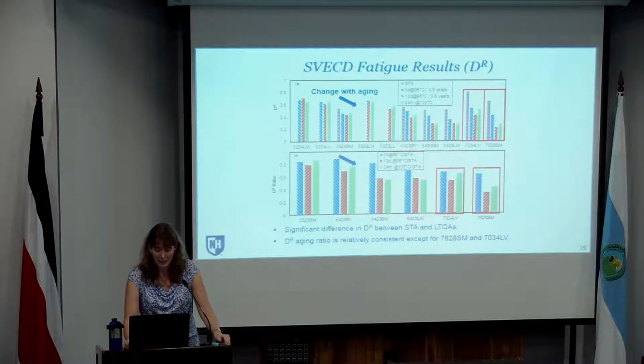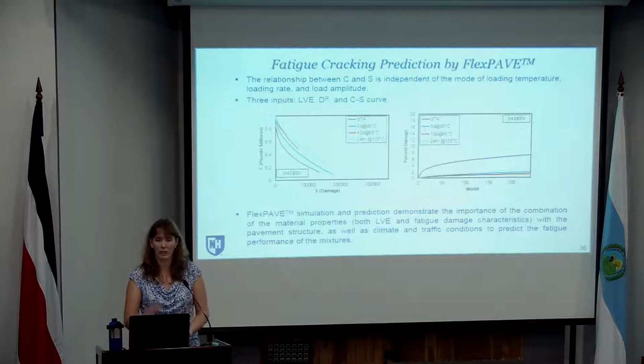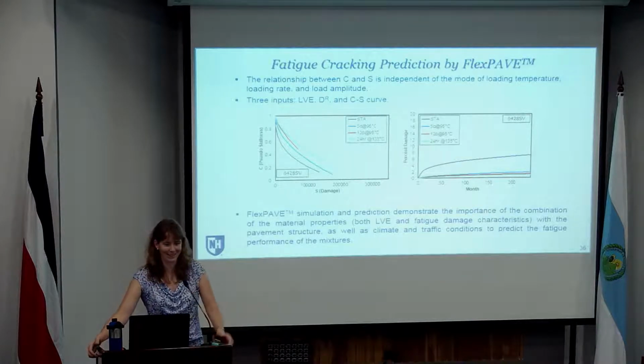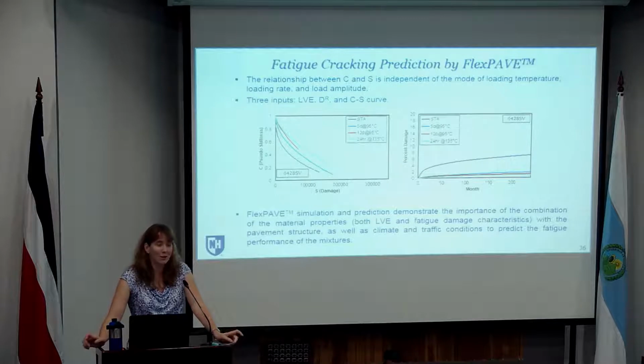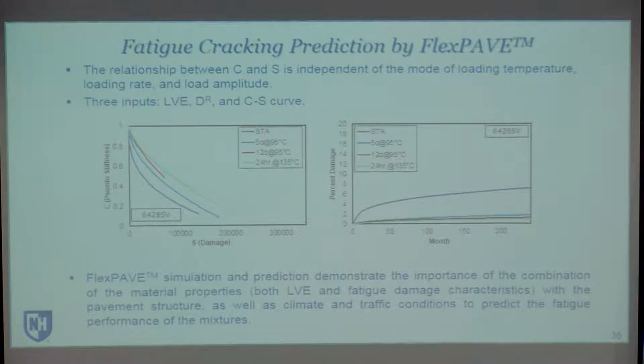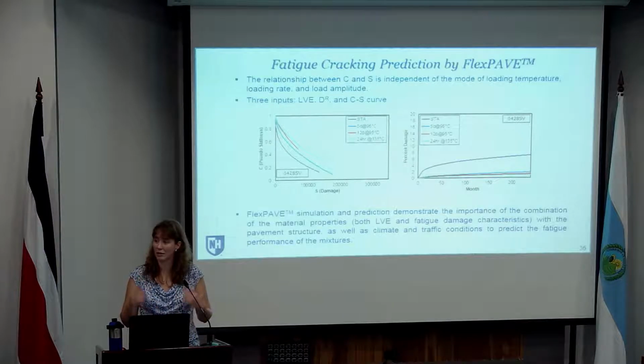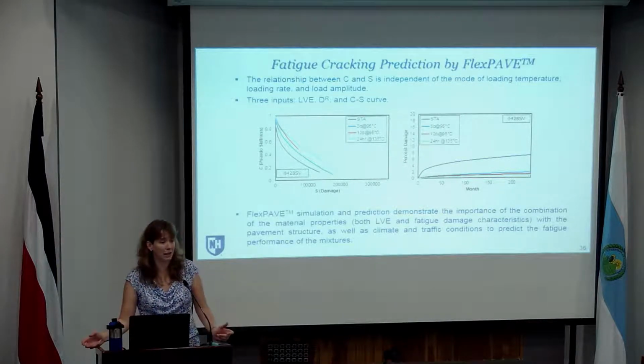So in terms of fatigue, the SVECD fatigue approach, the fatigue testing is also linked with a pavement evaluation. And I know John alluded to this. I walked in just in time to get this link back to yours in the morning. Especially when you're looking at fatigue, it's not just the property of the mixture. You've got to think about where that mixture is going to be placed in the pavement structure. So one of the things with the fatigue performance is what we've done is taken the results from the mixture testing, combine that with the viscoelastic response, and a pavement evaluation, so actually putting it into a pavement structure, and predict what the performance is going to be over time. And that can completely change things.